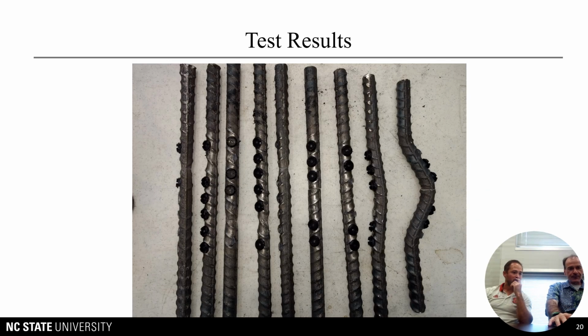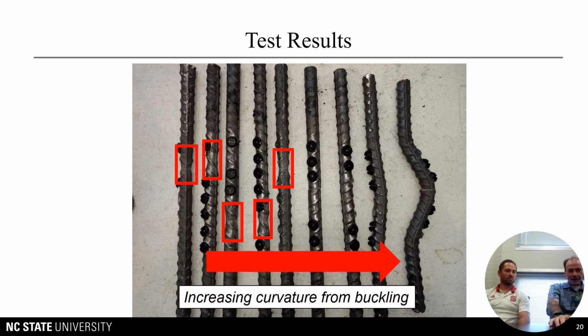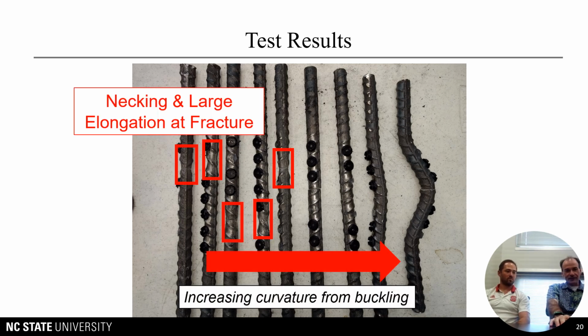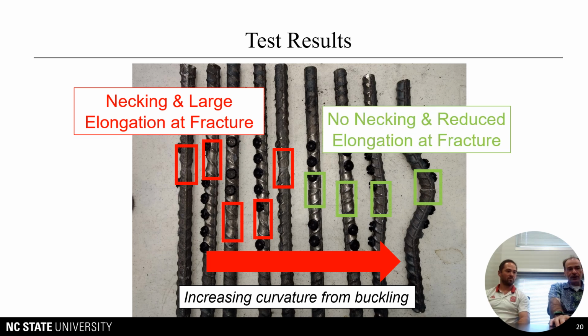Exactly. I think this was also interesting because it shows the nice progression that you were talking about, Leo. All these individual tests had been buckled, and then pulled to fracture in tension. Several of these early bars were able to recover that buckled shape and fail in a ductile manner. Whereas the one on the right is an extreme case, subjected to such a high level of bending strain that when you went back in reversal, it just immediately fractured. Yeah, and I think we divided those into the more ductile failures and the more brittle ones.